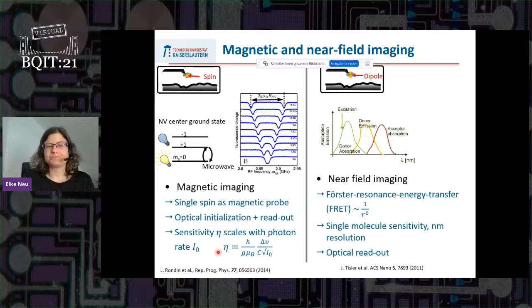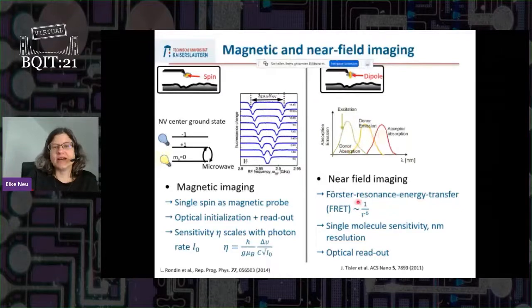On the other hand, your color center is also an electrical dipole. As an emitter of light, it has to be an electrical dipole. And as this, it can exchange energy with other dipoles that are close by. This is a process called Förster resonance energy transfer, or FRET for short. You have one dipole, the donor, that will be excited, but instead of directly radiating, it transfers its energy to an acceptor. And this process is highly distance dependent. It scales with one over the 6th power of the distance. So you can use this also as a tool for nanoscale imaging of the presence of other dipoles.